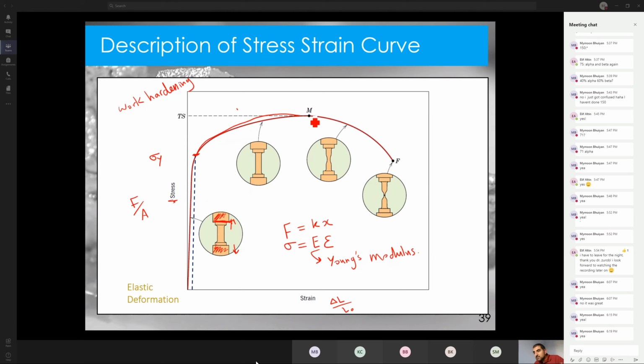Now you notice there is a maximum point here, and the reason there is a max and then the stress begins to decrease is the sample begins to neck down, it begins to thin down. So the sample is not getting weaker, it's actually still getting stronger, but we're interested in the force divided by the area, and the force is now getting concentrated over a smaller and smaller area. So the stress can continue to go up without having to increase the force. If the area is shrinking, I don't need to increase the force for the stress to go up, I just need a smaller and smaller area.